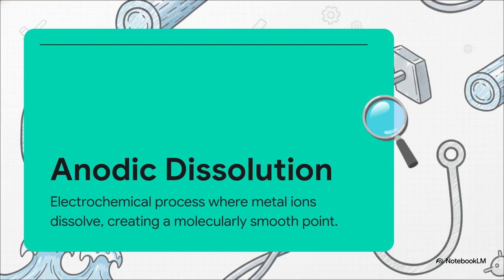The premium solution here is chemical sharpening, or electropolishing. This is where I totally geek out because it so brilliantly illustrates the intersection of chemistry and angling. Through a process called anodic dissolution, the hooks are submerged in an electrolyte bath of phosphoric and sulfuric acids. An electric current is passed through, and the metal ions dissolve. The acid attacks the microscopic peaks and burrs fastest, melting them away to create a surface that is perfectly, molecularly smooth. It refines the edge without introducing a single ounce of mechanical or thermal stress.